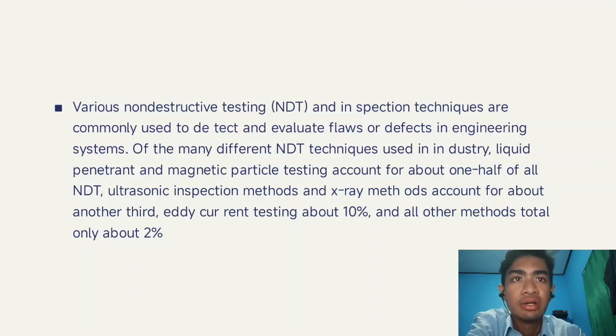This method cannot identify cracks or flaws in parts if the defects are filled with materials such as scale that can be produced during atmosphere annealing operations prior to inspection. In order for the crack to be detectable by these methods, it must be able to draw the liquid in, and the presence of scale or other material in the crack can prevent this from happening.